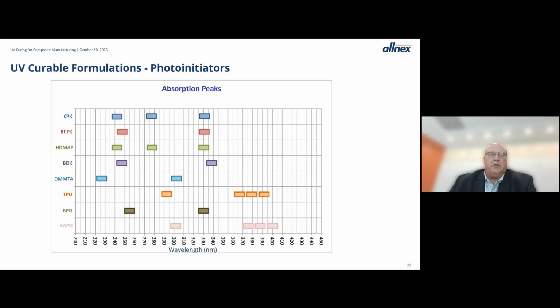And this chart just shows several common photoinitiators on the left side there, and where their peak absorbances are. Most of them have an absorbance around 240, 250, and another one around 330. And then you notice a couple down near the bottom that also have very long wavelength UV absorbances, the TPO and the BAPO. And these are materials that absorb in the areas where some of the newer lamps, the UV LED lamps, put out their energy. So they're very useful for curing with UV LED lamps.